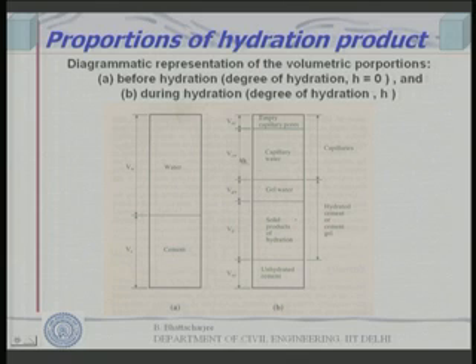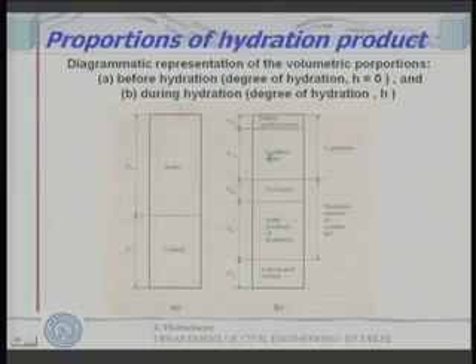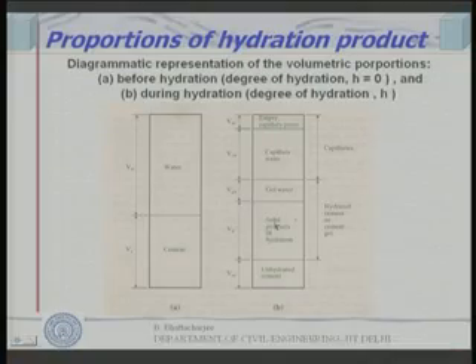In addition, we will have some amount of originally water filled space which will remain vacant or will be filled by water, we call this as capillary water, which has not been filled by the solid. But we shall also see that there is some amount of space which will remain empty capillary. Why? Because if you see the volume occupied by the water and solid cement earlier and the volume occupied by the solid product of hydration after reaction, we will find that there is a slight reduction in the volume. This occupies slightly less volume than the volume of water and cement that has been consumed in producing this. So, therefore, there is some amount of empty capillary formation always takes place while cement reacts with water.